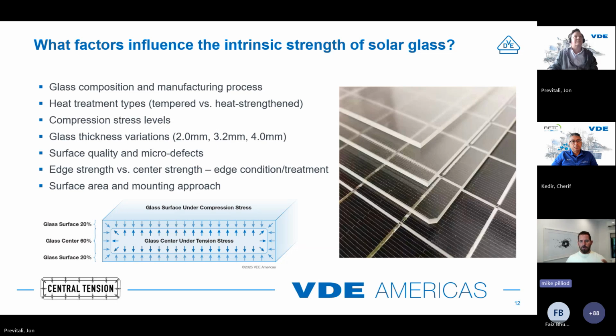The stress level, if you think about heat tempered and strengthening, I'll go into it in the next slide, but in general, it's the amount of compressive surface stress and then the depth of layer. So how deep the compressive stress goes into the glass. In thermal tempering, it's roughly about 20% on each side, and on the edges is compressive stress, and the inner 60% is under tension to balance that stress sandwich.